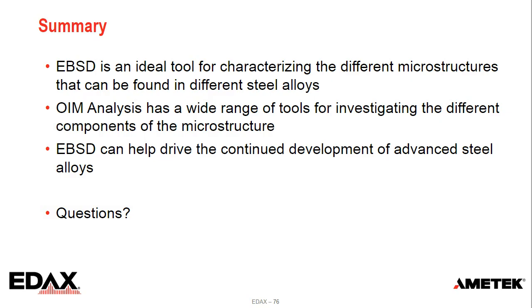And so here's a question: without EDS, will EBSD indexing be correct? That all just depends on the phases you're looking at. For example, if I'm looking at just FCC and BCC, a ferritic austenitic steel, EBSD does great with that. Or some of the carbides, the sigma phase, which is different, it will differentiate those, no problem. It's when the crystallography starts to be really similar that EDS is helpful. And then when they're similar both chemically and crystallographically, that's the martensite, they're both similar in both regards, then we have to use a third approach to try to differentiate those.